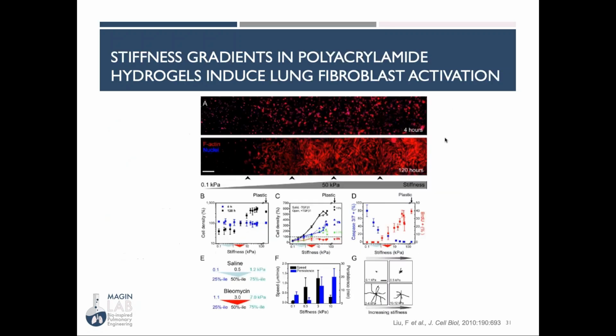But polyacrylamide has shown us some really interesting things in the lung. So in 2010, this work from Dan Tschumperlin's group showed us that if we create a stiffness gradient in a polyacrylamide gel from 0.1 kilopascals up above 50 kilopascals, you can see that we get a gradient of activation of these human lung fibroblasts when we grow them on the materials. They've also gone on to show that there are changes in migration speed and persistence based on the stiffness of the underlying matrix. And they've shown differences between healthy saline and bleomycin. This is a drug that is administered to mice to create a fibrotic lung response. They've seen differences in those cells on these different biomaterials. So it's been really fascinating to see this work emerging in the pulmonary field and to see this group building on it.